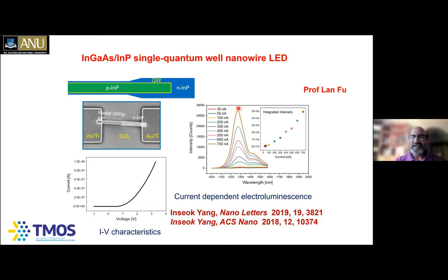But you do not see any narrowing of the line which I've shown you earlier. You also don't see any threshold-like behavior, which I've shown you earlier as well. So that tells us that they're acting like nanowire light emitting diodes, LEDs, but not like lasers. This particular work has been led by my colleague, Professor Lan Fu. So you can see, you ask the question, why?